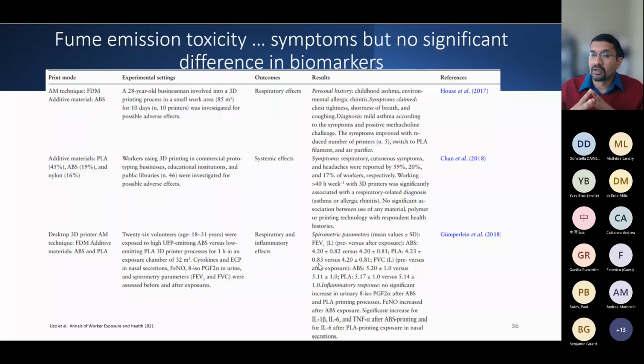If you use this data and you compare and contrast to either cellular studies or animal studies, the reactive oxygen stress, ROS, and then when you talk about inflammatory markers, in cellular and animal studies, they are showing that they are significantly higher, but you don't see the similar response in human health studies. By no stretch, I'm a toxicologist, but that was insightful for me to kind of see how the data across species is different, both at the biomarker level. That gives us an indication of where we think around risk control and how we can mitigate this when it comes to additive manufacturing.